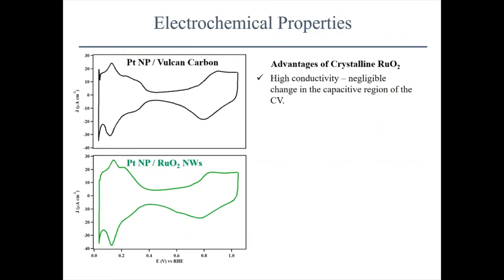So then the next phase was to compare these catalysts, the traditional support to the ruthenium oxide support, in terms of the electrochemical properties. And we can do this by cyclic voltammetry. One of the things that you might be worried about using a metal oxide support is low conductivity. Metal oxides tend to be either semiconductors or insulators. One of the reasons why we chose ruthenium oxide was because this tends to be relatively conductive. Of the different metal oxides, it's one of the metallic metal oxides, so it should be relatively conductive.